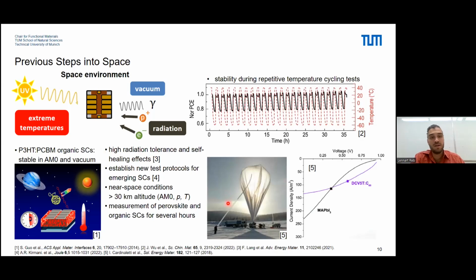And in this regard, balloon flights have been the first step, where in such stratospheric balloons, the solar cells can be exposed at above 30 kilometers altitude to near space conditions. Cardinaletti et al. 2018 published work where they measured organic and perovskite solar cells for several hours in these conditions, and they worked. And recently there's a new work with even organic solar cells of more than 3 watts per gram on such a balloon. So it's also possible to do these kinds of experiments with flexible, lightweight solar cells.